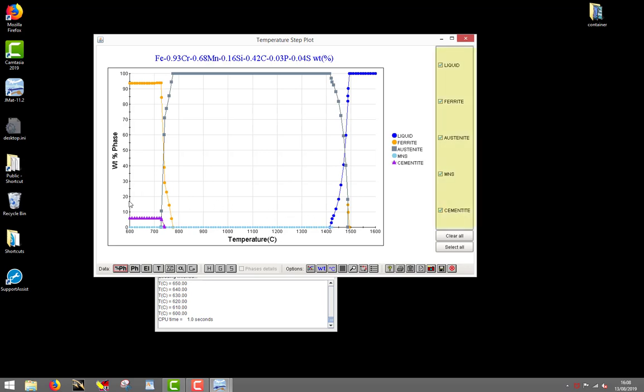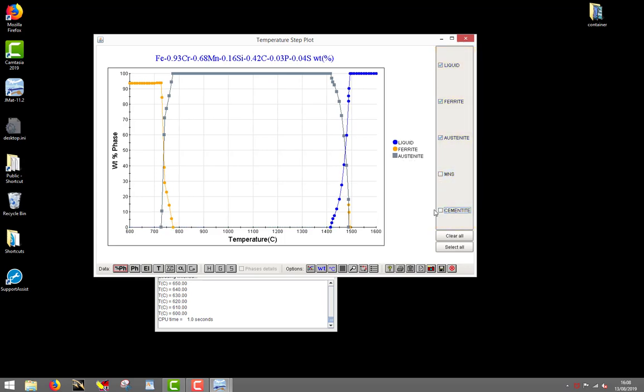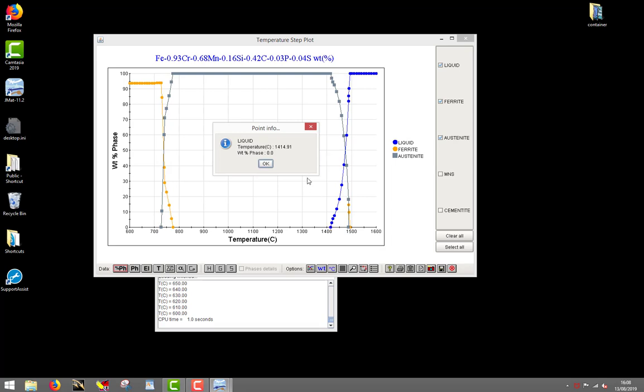In the right part of the window, you can choose to include or exclude phases from the display. By clicking on any point in the graph, you can get the coordinates of the point, which in particular allows you to easily get critical temperatures like liquidus and solidus. For instance, if I am looking for the solidus value, I would here get the value of about 1415 degrees Celsius.